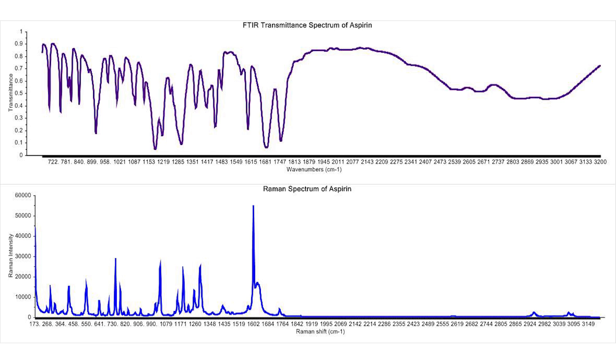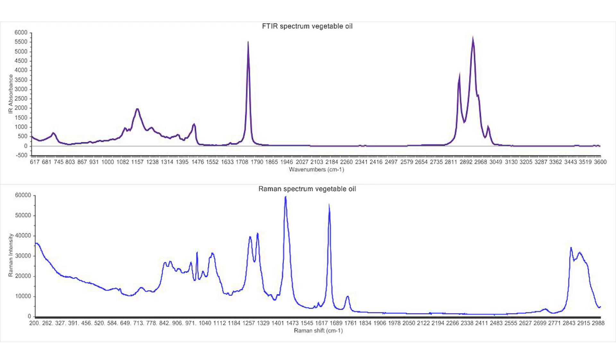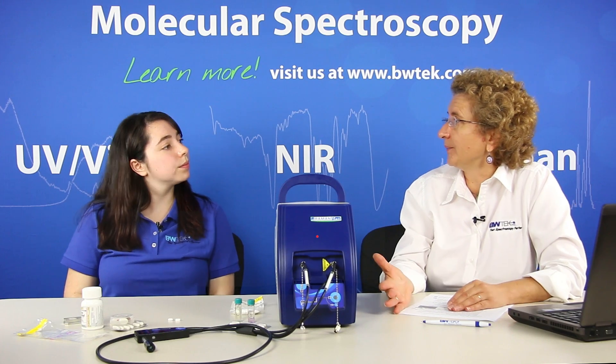Things that are strong in the Raman are symmetric molecules, because we have a change in polarizability that comes from the Raman effect. Whereas with infrared, it's a measurement of the change in dipole moment. So polar molecules tend to have much stronger infrared spectra than Raman spectra. A polar solvent like water has a very strong IR spectrum, whereas it's quite weak in the Raman, which gives us an advantage with Raman in that we can use it in measuring aqueous systems — which is quite challenging when using IR spectroscopy.